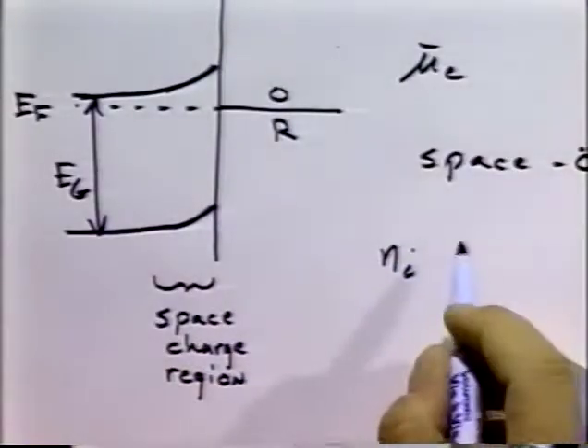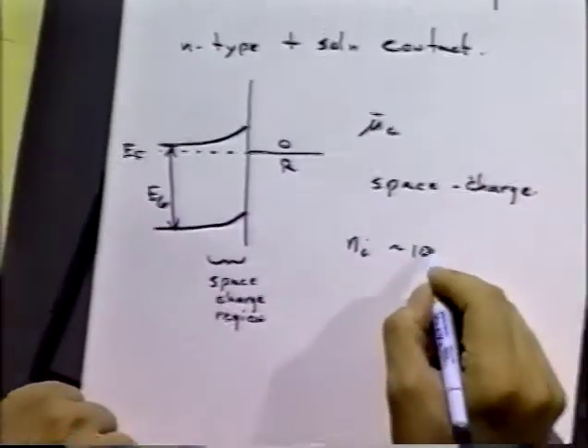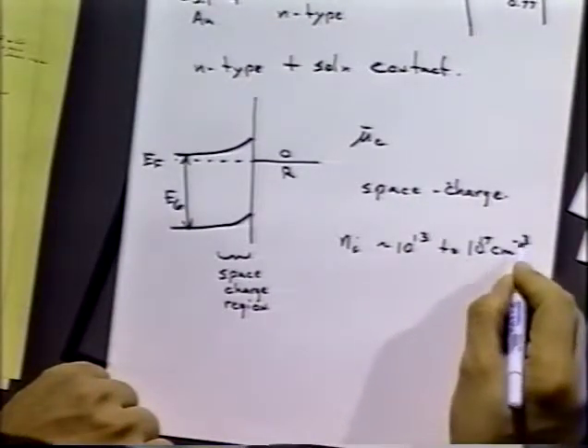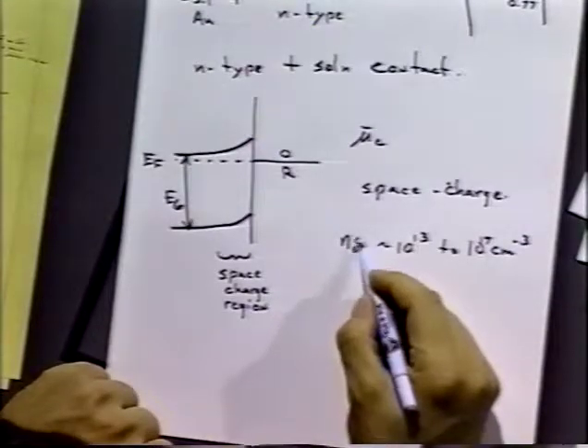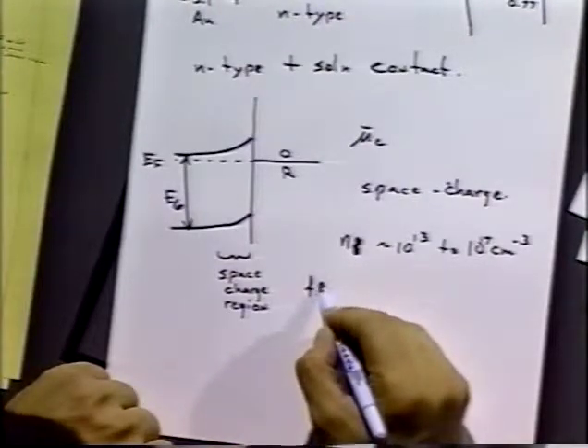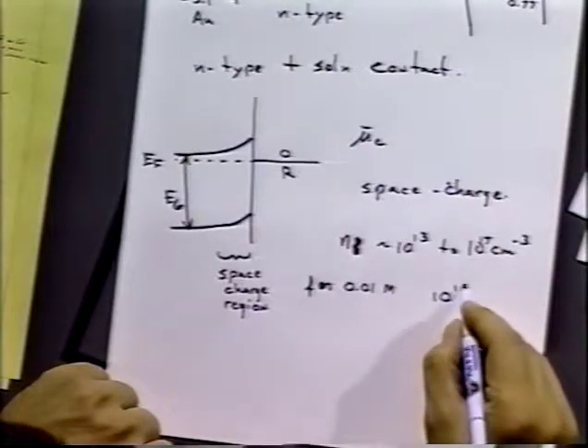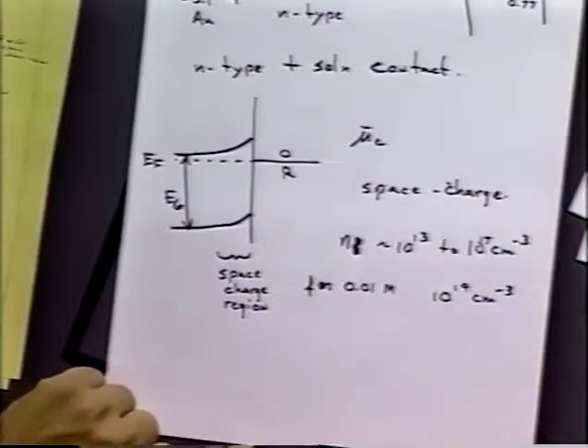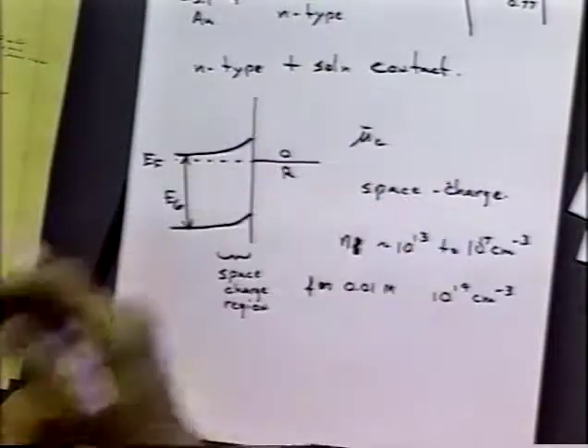Let's compare. For a semiconductor, the number of intrinsic carriers is going to be about 10^13 to 10^17 per cubic centimeter, and we might just call that the number of carriers. If we have a 0.01 molar solution of electrolyte, there's going to be about 10^19 ions per cubic centimeter in that system. And so in that case, there are more charge carriers in the electrolyte than there are in the semiconductor. And so you can see why we would have that sort of situation.